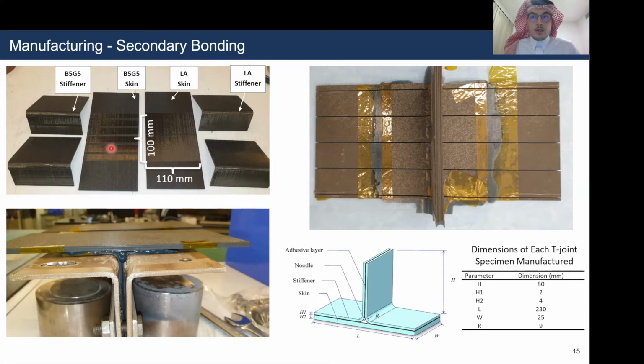Once the skins and the stiffeners were laser treated, they were secondary bonded using an Araldite 420 A/B adhesive, and they were cured. I just want to highlight here that the mold is actually flipped this time, because we wanted to ensure that there are no air entrapments or no voids inside the adhesive. So they were flipped and bonded together and inserted into the oven, and they were cured for 3 hours, the first 15 minutes under vacuum, at 60 degrees.